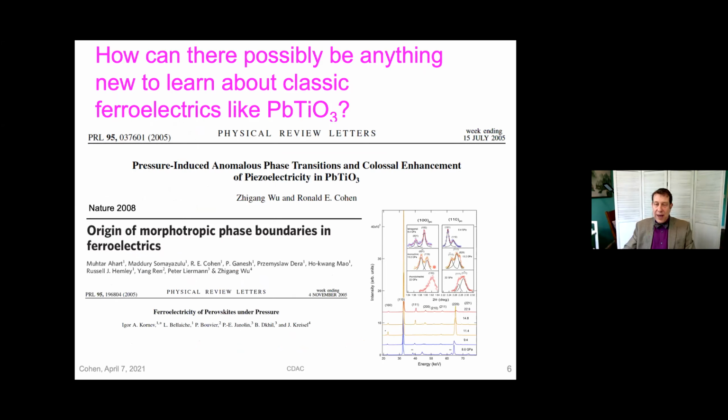We did some theoretical work first, and then some experimental work on lead titanate under pressure, and we found something very surprising. In the process of becoming cubic, it seemed, there was a set of phase transitions where it became monoclinic instead of tetragonal, and in that phase transition region, we predicted some extremely high piezoelectric coefficients, in fact, higher than have been observed for any known material.